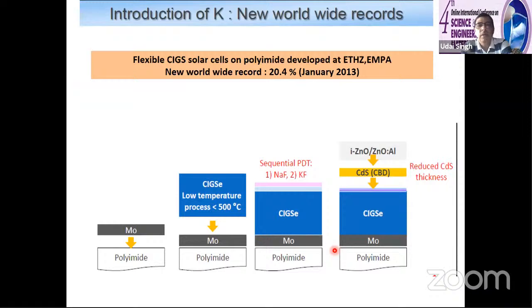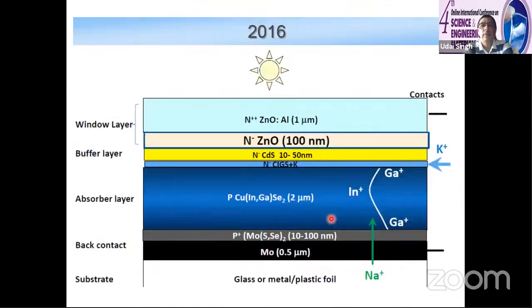So for the flexible, the polyimide moly process is the same. The only thing is you cannot go above 400, because this polyimide substrate can take a maximum temperature of around 450. So you have to deposit CIGS at less than 500 degrees C. The rest of the process is the same. So this is the standard process people are using now.